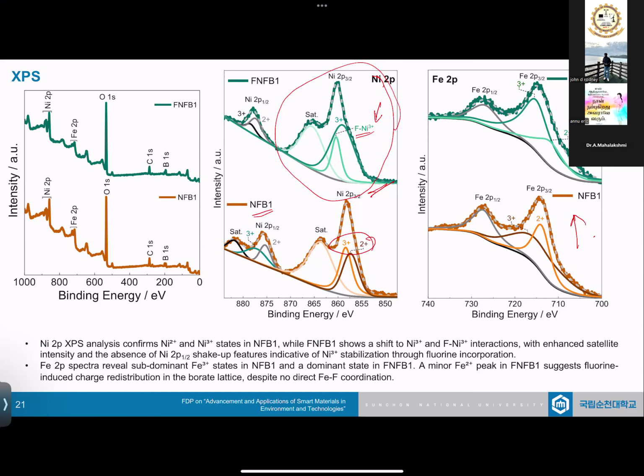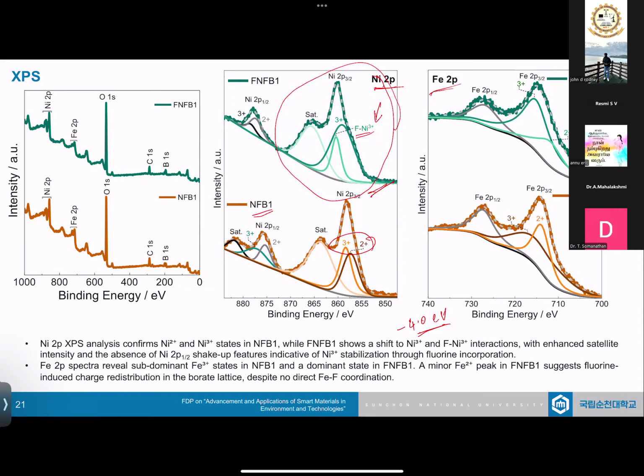The reason we looked into nickel and iron in the beginning is because of the Hubbard values; I think nickel has around minus 4.0 electron volt or something, that much affinity in enabling a reaction. Whereas we know that fluorine is chemically bonded, but we don't know how, where, and what it's doing. We are trying to understand which one it's sitting on. So through this, we can vaguely understand that maybe the fluorine is bonded to nickel more.